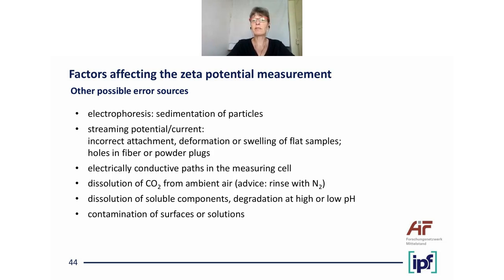And a very big influence is the dissolution of carbon dioxide from ambient air. That's why we always rinse our measuring solution with nitrogen. If the carbon dioxide is dissolved, you get a lower pH value than you expected. You also have to take care that your sample does not contain soluble components that are dissolved during the measurement, or sometimes there may also be degradation of the sample at high or low pH value. And you have to take into account that Zeta potential measurements are very, very sensitive to contamination, both of the surface you measure and of your measuring solution. So you have to work very carefully.